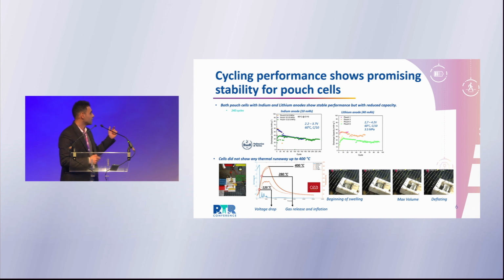So then we heated up this cell, and we saw that at around 120 degrees, the voltage is lost. At around 280 degrees, some gases started to release, and at 400 degrees, so we heated up to 400 degrees, and you can see the pictures on the right side. So the cell was safe. At around 280, some gas released, but no real thermal runaway took place in these cells.